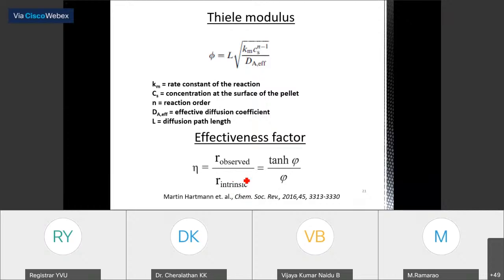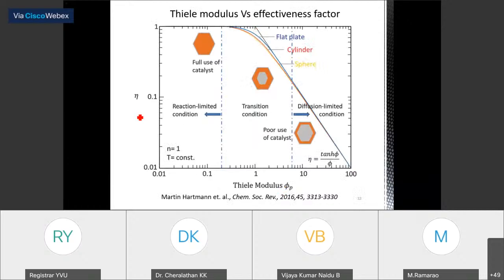It is nothing but the rate of the reaction observed, divided by the rate of the reaction intrinsic. So what is this effectiveness factor? If this ratio between the observed rate and the intrinsic rate is 1, then you are using the catalyst 100%. Okay? Like that you can imagine. It is nothing but tanh of the Thiele modulus divided by the Thiele modulus. So when you plot this effectiveness factor against the Thiele modulus, you will get a graph like this.